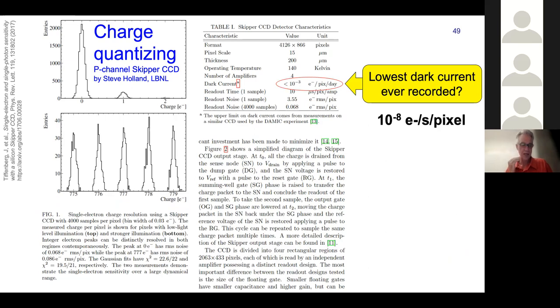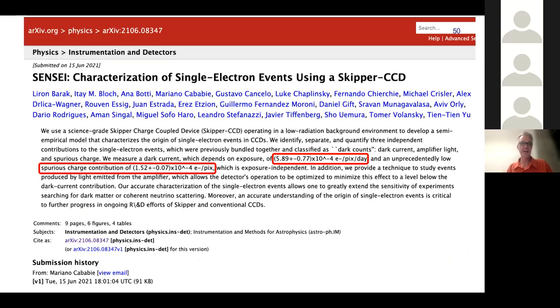And to boot, this particular device has actually registered a dark current of 1 electron per pixel per 1,000 days. And there was some skepticism in the field about this. And so the team burrowed down and redid the measurements and wrote a paper dedicated to just this and released the paper a few days ago. And now they've got error bars on the number. So they've actually reduced their estimate of what the record dark current is. Unfortunately, this measurement was made in a device that takes about an hour to read out because of this skipper mode. And one would need to respin the design to have maybe 100 output amplifiers in order to get that readout time down to reasonable numbers.